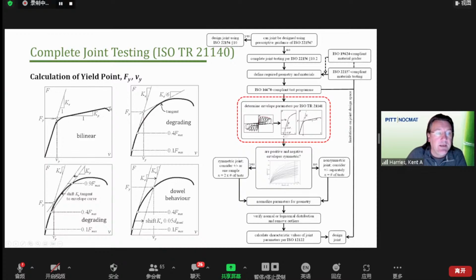So is it a bilinear curve, in which case we just draw a secant having a stiffness of K sub P. If it's a degrading curve, we use 1/6 of the elastic stiffness. We can use secants and offsets down here with degrading curves as well, or more of a typical offset method if we're looking at dowel behavior. In the case of this particular study, we used the bilinear approach. Most of the data was fit bilinear very well, in which case we have our rules for finding our yield point. We have our initial stiffness K sub E. We extend our post-peak stiffness backward until it intersects with K sub E, and we define the yield at that location. All of this is part of 21140.